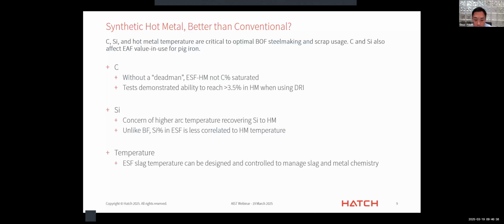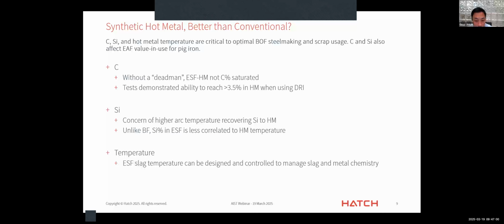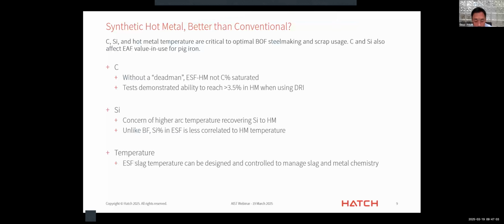Again, down to the temperature, because of the electrical control of the energy balance, the temperature of the slag can be controlled and adjusted very quickly, which not only makes the overall control of your process much easier, it also allows precise control of slag without upsetting the entire iron making process like in the blast furnace. In a blast furnace, you don't really directly control the slag quality or the temperature. It's more about the recipe control and some control in the fuel rate, which again impacts your slag make, for example. So very precise control of the slag temperature and composition is quite difficult there, but that's something that can be very precisely monitored and controlled in the ESF, which provides all these other benefits to the hot metal quality.